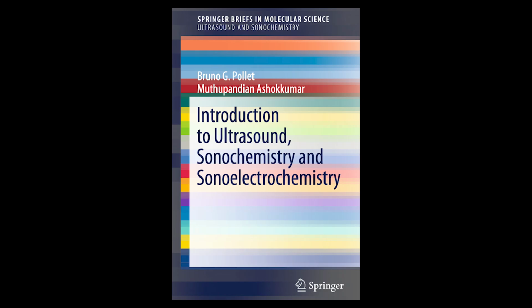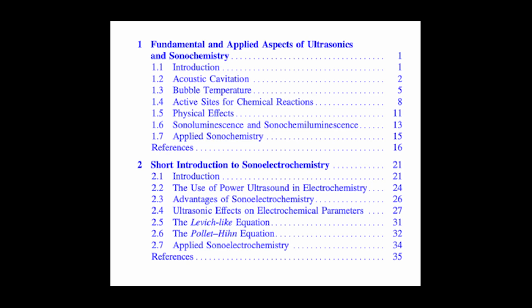Makes sense. Does it affect the energy required? Yes, critically. Because you're overcoming these limitations, the electrode reactions can proceed closer to their thermodynamic ideal. This means you often see a decrease in electrode overpotentials. Overpotential, that's the extra voltage you need to apply beyond the theoretical minimum to get the reaction to go at a decent rate. Exactly. It's like electrical friction or resistance in the system.